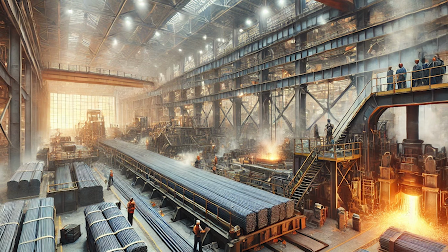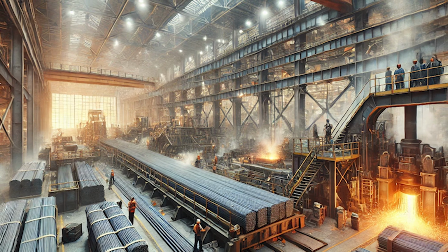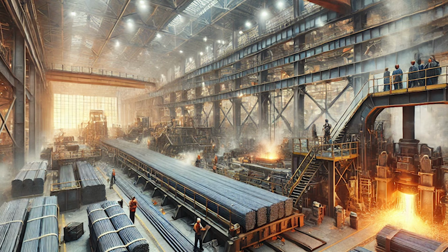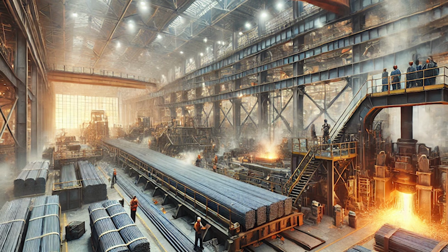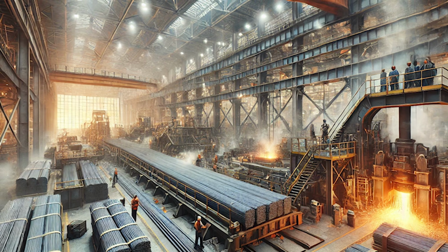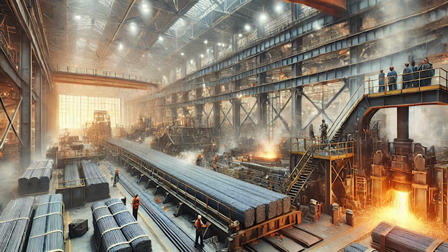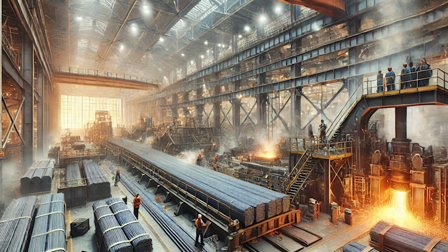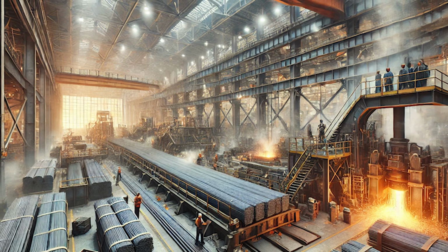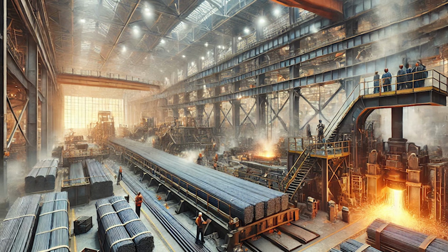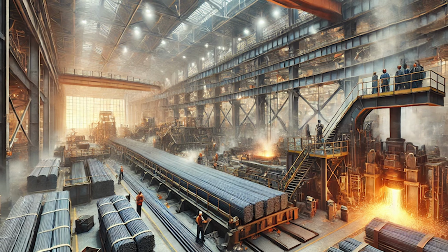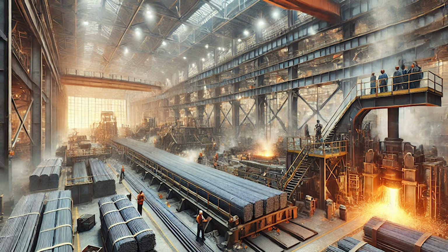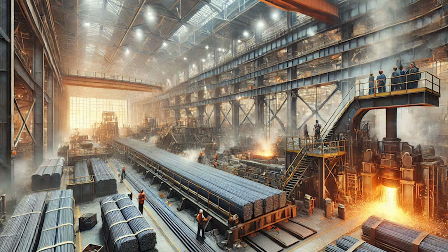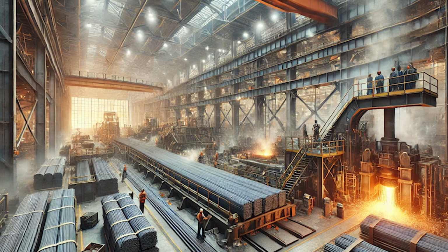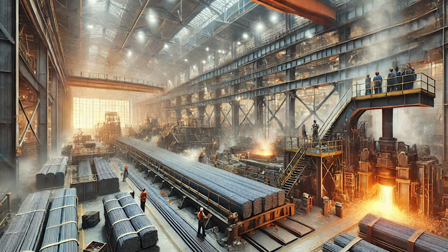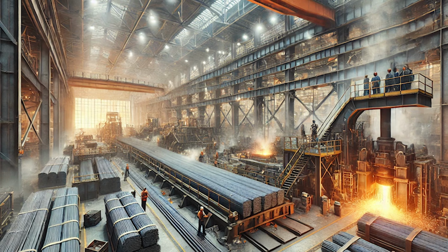The homogenizing furnace transformed billet quality in ways that exceeded Reynolds's projections. Chemistry uniformity improved by an order of magnitude, eliminating the composition variations that had occasionally created weak spots in finished bars. Microstructure became remarkably consistent, with grain size that remained uniform from bar surface to center. The extended heating cycle also eliminated internal stresses that could contribute to delayed cracking under service loads.